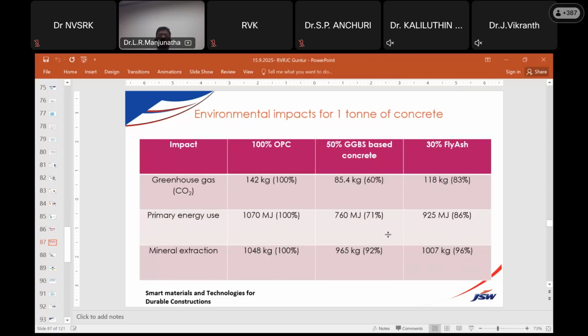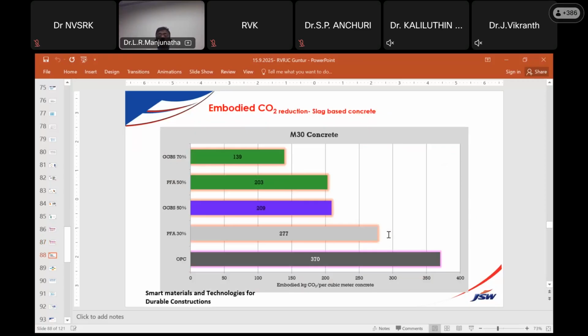Environmental impact for 1 ton of concrete, when making concrete using blended materials like GGBS or fly ash, is also very good compared to 100% OPC mixes. A 50% GGBS mix comes with 85.4 kg with respect to 142 kg for OPC mixes. If you're using 30% fly ash, it's 118 kg of greenhouse gas emissions. Primary energy usage also gets reduced. Mineral extraction also gets reduced, because using these smart materials and smart technologies is always impacting the environment positively, also reducing the carbon footprint.